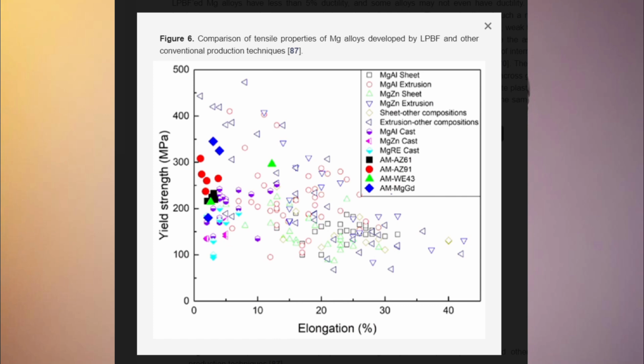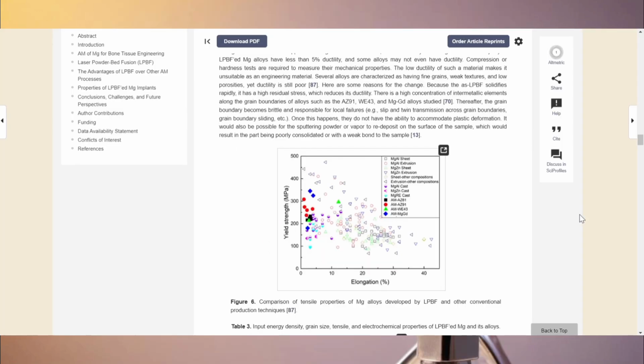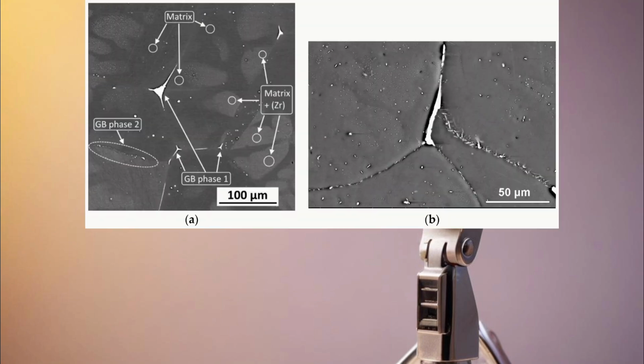This limitation makes compression and hardness testing essential for assessing their mechanical properties. But altogether, I can say, unfortunately, such poor ductility means that many LPBF magnesium alloys are not ideal for engineering applications. It is noteworthy that even when these alloys have fine grains, weak textures, and minimal porosity, their ductility remains insufficient. Several factors contribute to this. The rapid solidification process in LPBF creates high residual stress, so it directly impacts ductility. Additionally, in alloys such as AZ91, WE43, and magnesium gadolinium, intermetallic compounds tend to accumulate along the grain boundaries. This weakens the material, making these boundaries prone to localized failure.